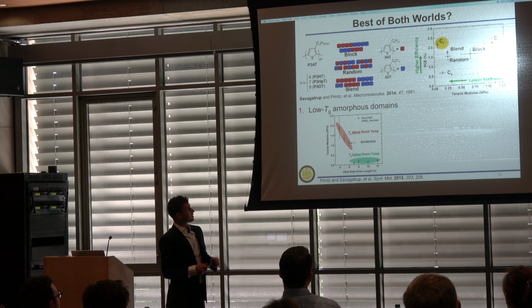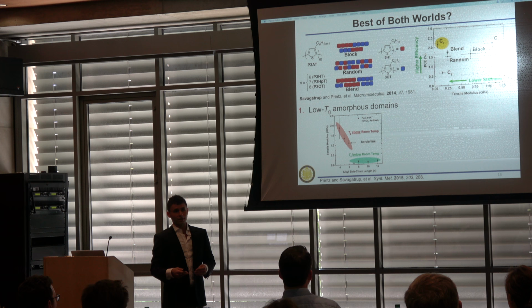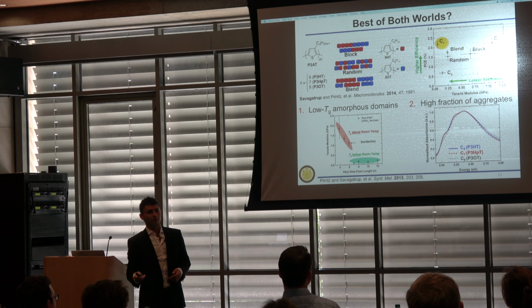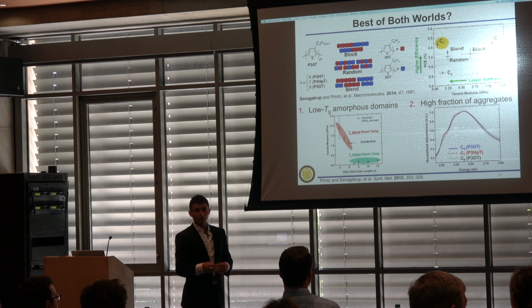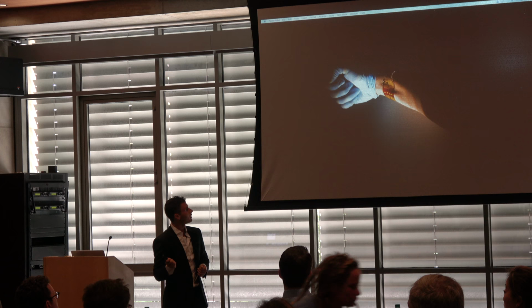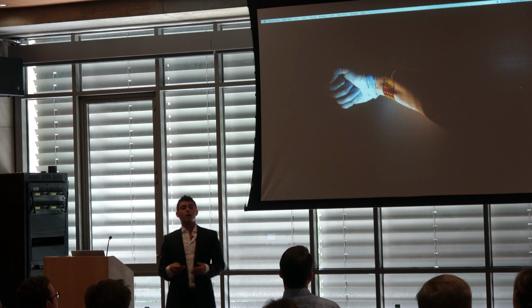And the reason for this is C7 is the first material to have a glass transition temperature below room temperature, but it also had a high fraction of aggregates. So the high fraction of aggregates would carry charge, but since it had still enough amorphous domains, it was able to accommodate that strain within its molecular structure. So my job was to use this knowledge to build something. What could we build today that we wouldn't have been able to build yesterday without it?